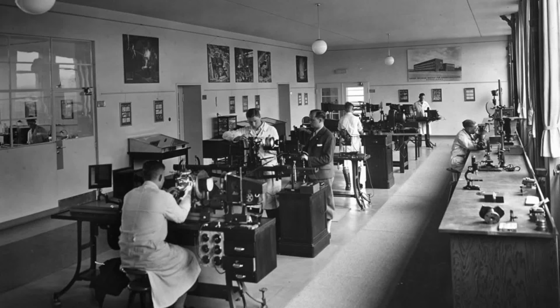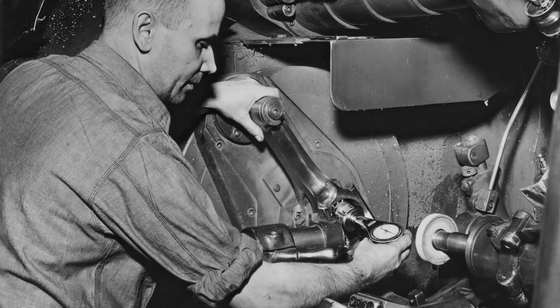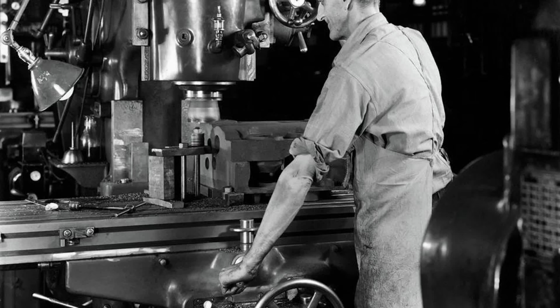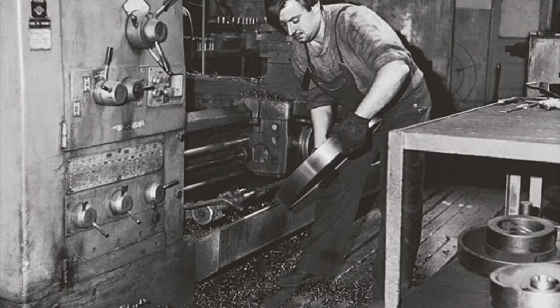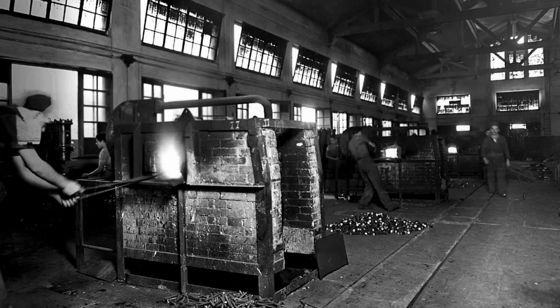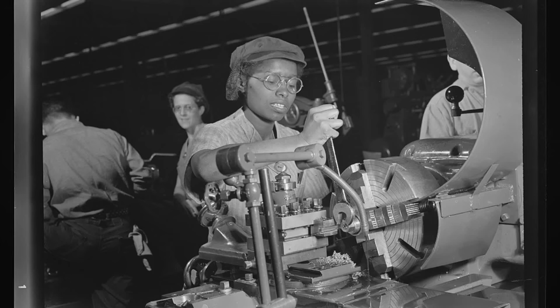It kept spending money. The company treated the failures as information. If a carbide tip broke at the joint, improve the brazing. If it fractured because the steel support flexed, redesign the holder. If the edge chipped because the cutting geometry was wrong, change the geometry. If one batch performed differently from another, improve powder preparation and furnace control. If a customer destroyed the tool by running it like high-speed steel, teach the customer how carbide needed to be used. This last point mattered enormously.